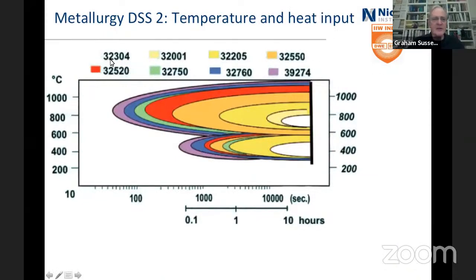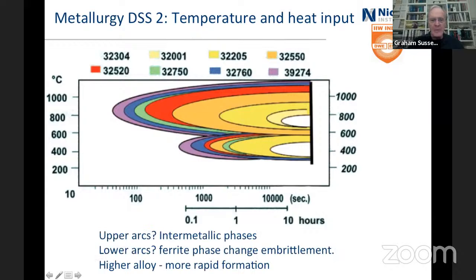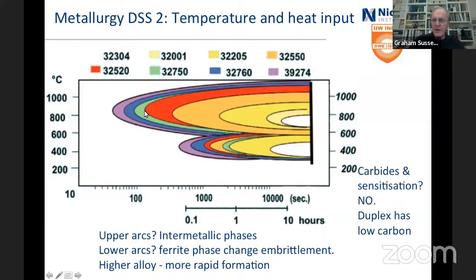These are all duplexes, 2304, 2001, 2205, 2550, etc., etc. And all of them have this double curve arrangement, and all of them, the ones that are right up at the far end here, are the ones that go quickest. But this is in seconds or in hours down here. Upper arcs, intermetallics, lower arcs, the ferrite change, the alpha to alpha prime. Higher alloys, you have more rapid formation. Carbides, I've said carbides really aren't usually an issue.